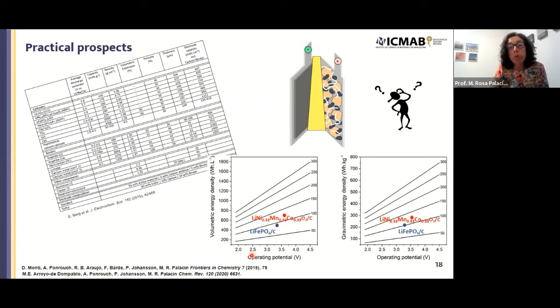So we suppose that we can find a positive electrode material that would operate between 2 and 4.5 volts and would have different values of capacity, 50, 100, 150, and so on. For instance, if we are able to develop a material which has a capacity of 150 milliamp hours per gram and that works at 3.5 volts, we would be on par with the best lithium-ion battery technology at the moment, the highest energy density, the NMC graphite. This graph is volumetric, this one gravimetric, but the results are the same. And this is not really such a huge value.